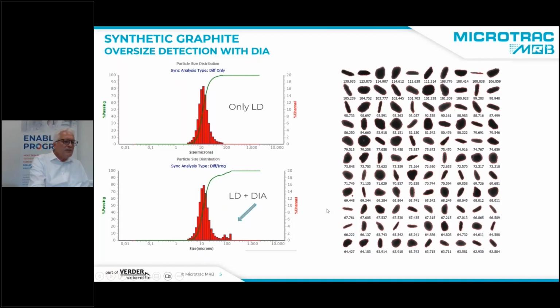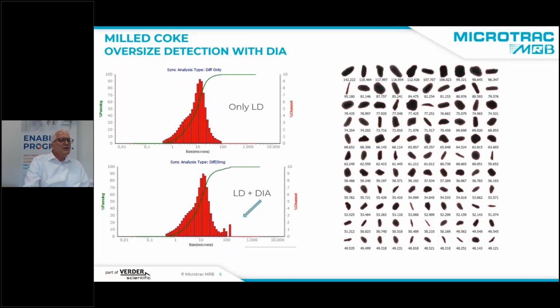And when we do this, we get the combined information of laser diffraction and dynamic image analysis showing us the oversize. This may have an impact also on the performance of a final electrode. You don't want to have these kinds of oversized particles. Another example is milled coke. We again have a particle size of about 10 microns only with laser diffraction, and with the help of dynamic image analysis, we can detect even particles above 100 microns, and you get a much better impression and knowledge of your material.